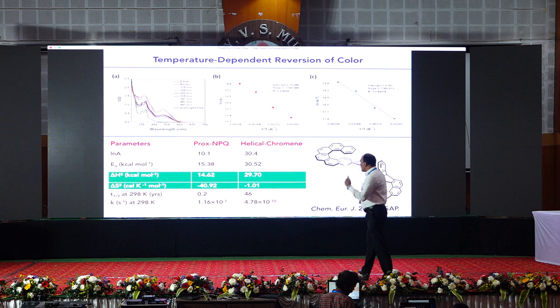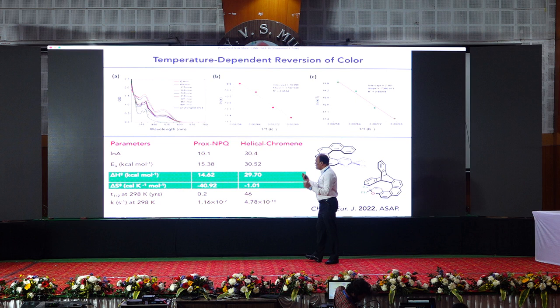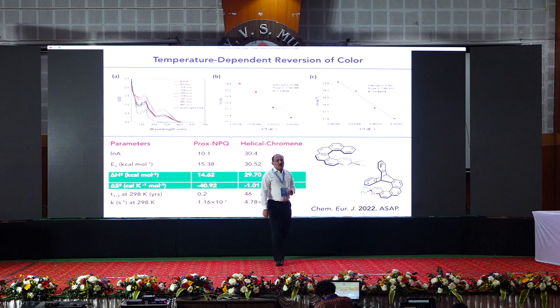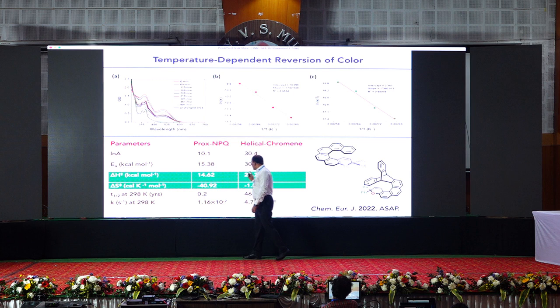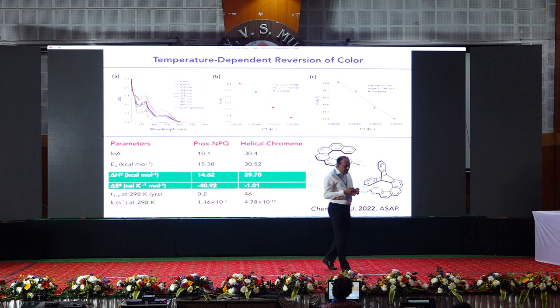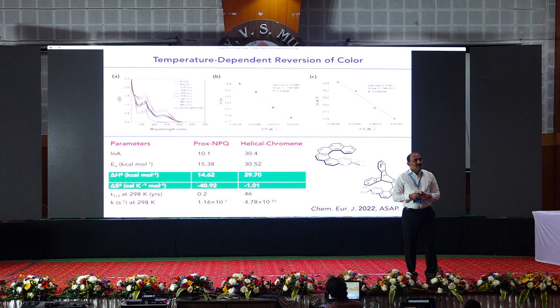And you can basically look at the parameters here. And you do the temperature dependent analysis and come up with entropic factors. When you have Prox-NPQ, it's about -40.92 or whatever units for the entropy. Enthalpy is only 15, vis-a-vis the helical system where it was about 30. In fact, any process with about 15 to 16 kilocalories of enthalpy of activation should occur very easily at room temperature, if it is not for something else. And the something else here is the entropic factor. This is just to show you how you can develop materials at your will.